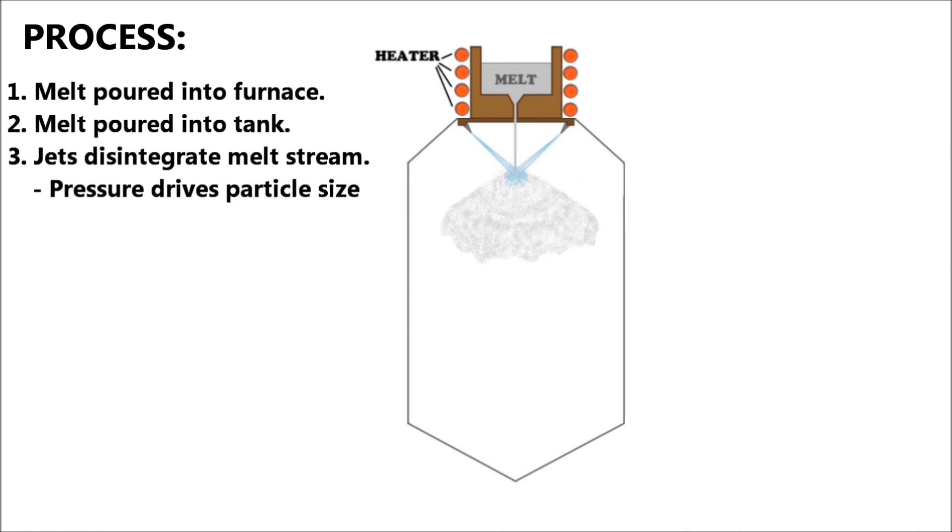Some of the liquids you could use include water or oils, with water being the most common fluid for low-reactive materials that melt below approximately 1600 degrees Celsius.